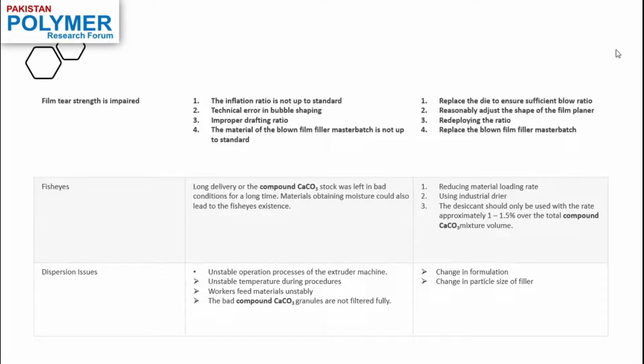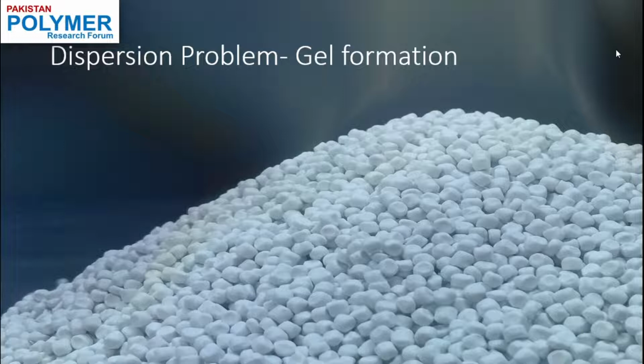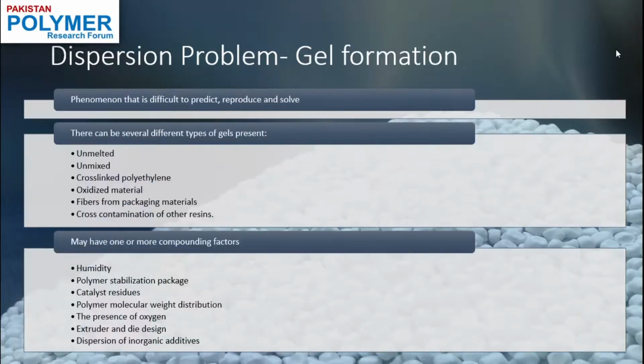One of the major dispersion issues is the gel formation. It is major because it is very likely to occur and it is difficult to predict and hence to solve as well. There are different types of gels that can be present in your film, such as unmelted gel, unmixed gel, cross-linked polymer, oxidized materials. Impurities from a foreign environment can be caught in your material. You can get contamination, especially when you're using a recycled material.